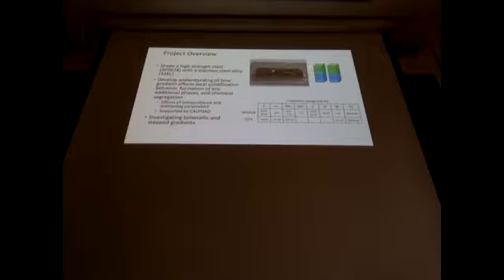We did both a gradient, where we tried to put a distance between the deposited Air Force 9628 alloy and the stainless steel, and we also did a bimetal grading as well. So we basically went to the Air Force alloy and then cladded stainless steel right on top of that. The idea is that we'll build upon this so that we can build some tensile bars that have some unique geometry within that grading seat, and then we can do some imaging, understanding the strains as it goes through tensile.